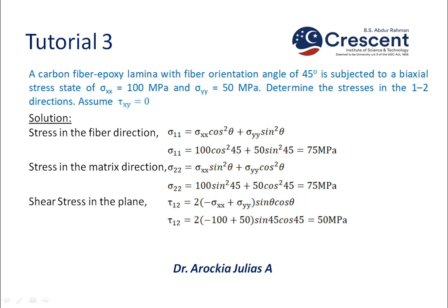Sigma 11 equal to sigma xx cos square theta plus sigma yy sin square theta. So substituting the values, sigma xx is 100, sigma yy is 50, angle 45. We get the sigma 11 as 75 megapascal. Similarly, stress in the matrix direction, sigma 22 equal to sigma xx sin square theta plus sigma yy cos square theta. Substituting the values, cos 45 and sin 45 are both 1 by root 2. So the values are the same, both in the fiber direction and the matrix direction the stresses are the same because of the angle 45.